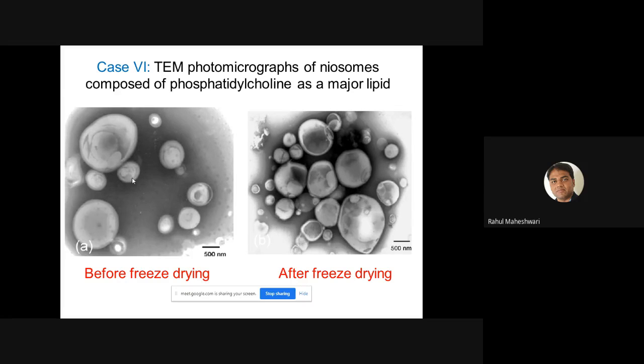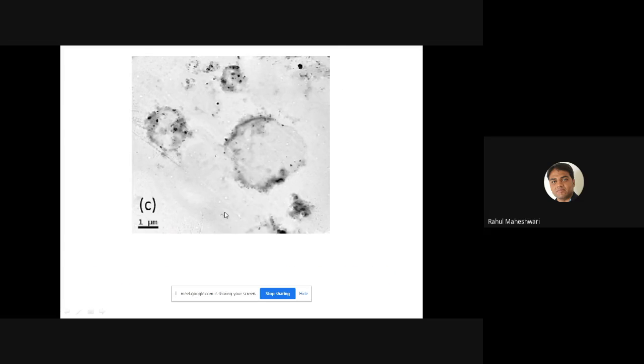So if you see these images, we can say that they are identical in nature and there is no change before and after the freeze drying. Just if you look at these circles, which are due to the incorporation of the cryoprotectant, that was trehalose in that case. Now, what is this?